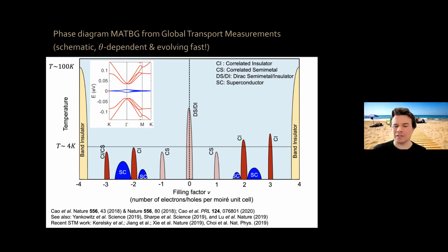If from charge neutrality, you remove 4 electrons or you add 4 holes per moiré unit cell, you reach the bottom of the valence band here. So your chemical potential goes here, where you have, again, a single particle band insulator, and that's the behavior that we see. Remember, I told you that electrons in graphene have this 4-fold degeneracy: spin up, spin down, valley K, valley K prime. That's why you go from +4 to -4. You also have 2 layers. So in total, you can put 8 electrons per moiré unit cell in these flat bands.